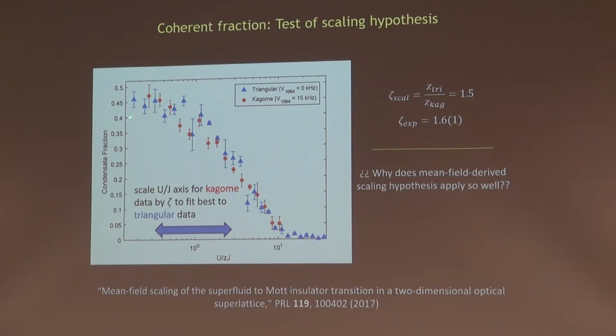So our best fit of the triangular to Kagome data means that we would expect to scale the interaction energy in one case by a factor of 1.5 to match data from one lattice to another. Experimentally, that works out within whatever the 6% error of our experiment. It leaves open the question of why this test worked out so well, because it's clear that mean field theory is terrible for this system. Particularly for a two-dimensional lattice system, mean field theory is awful, but somehow the scaling hypothesis flies through with flying colors.